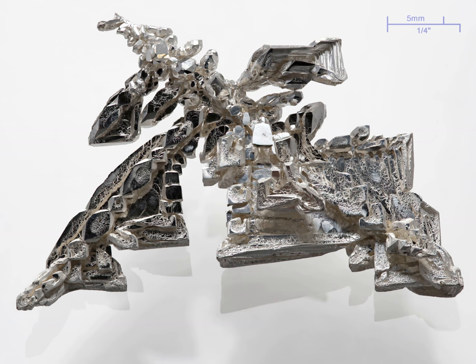Silver has a brilliant white metallic luster that can take a high polish, and which is so characteristic that the name of the metal itself has become a color name. Unlike copper and gold, the energy required to excite an electron from the filled d band to the sp conduction band in silver is large enough, around 385 kilojoules per mole, that it no longer corresponds to absorption in the visible region of the spectrum, but rather in the ultraviolet. Hence, silver is not a colored metal.